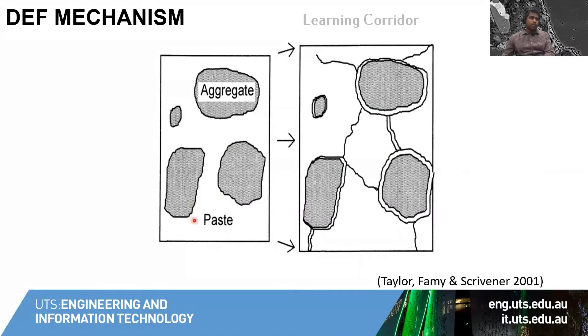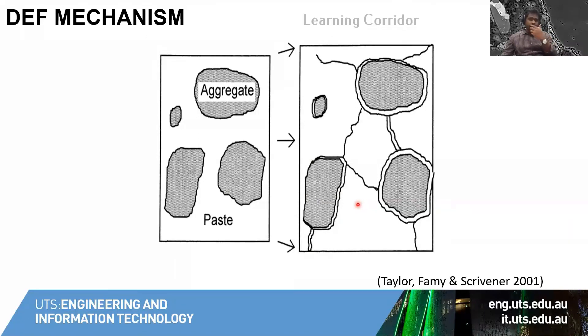In a normal situation, we can see here the interface between cement paste and aggregate. If delayed ettringite formation (DEF) is occurring in heat-cured concrete, the ettringites will get precipitated along the paste and aggregate interface, and this will actually create cracks, making the microstructure weaker. Once the microstructure becomes weaker, it leads to all sorts of durability issues.